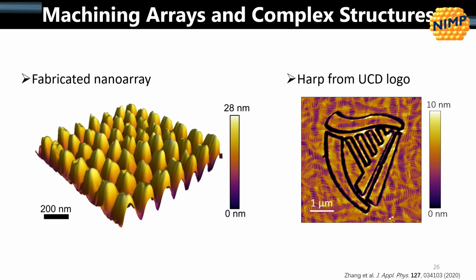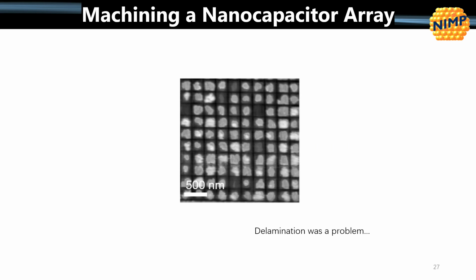So I was surprised how well this worked. For other materials, it doesn't work this nicely. We've looked at lithium niobate and some other materials. If it's brittle, you can end up fracturing and getting cracks. But for the right material and the right force, the right regime, you can get these nice structures.